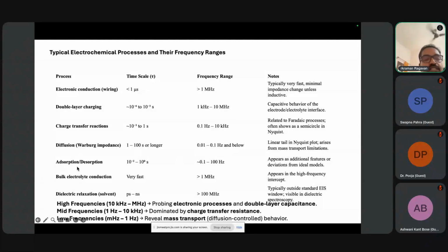Suppose you have adsorption and desorption in the process, then it would be between 0.1 to 100 hertz region. And if you look at the bulk electrolyte conduction, that means the conductivity, if it is very high, then you would see them responding at high frequency. But in general, if you categorize, at high frequency region you will be able to probe the electronic processes and the double layer capacitance. In the mid frequency regions, you will be able to look at the charge transfer resistance, and in the low frequency region, you will be able to look at the mass transport processes.